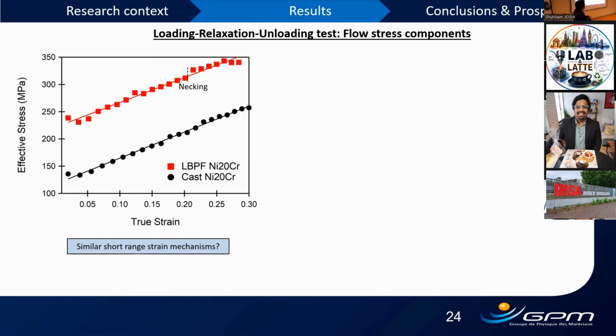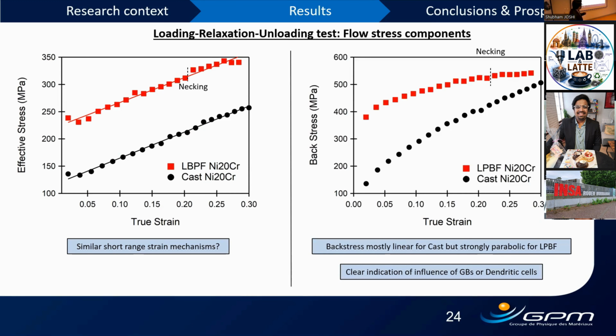What we see here is that the evolution of effective stress versus true strain is the same for the additive manufacturing or LPBF sample and cast. There is an initial difference, but it is due to the initial high dislocation density which exists in LPBF samples. So locally, or at least in short range interactions, we do not see any influence of the process. But when we consider back stress versus true strain for LPBF in red, first of all, the absolute value of initial back stress is much higher than effective stress. So certainly at yielding, something is happening due to back stress.